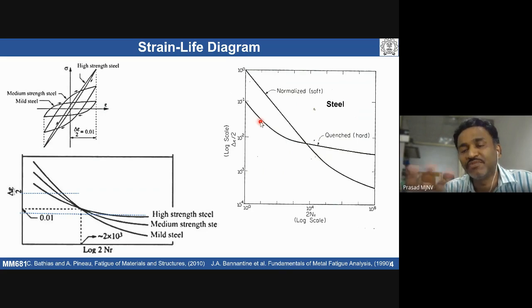First of all, in martensitic steels it's very easy to generate more cracks as compared to a normalized steel. The martensite laths or plates have sharp edges, which will act as stress risers, so we are going to create cracks very easily. The crack can be nucleated very easily and can also be propagated very fast because we have limited ductility in hard martensitic steels. In the case of normalized steels, the number of cracks is less to begin with, and even those cracks will not propagate very easily. Crack blunting is going to take place, so crack propagation is also going to be controlled. That is the explanation for low cycle fatigue.